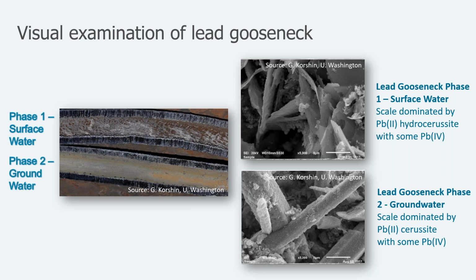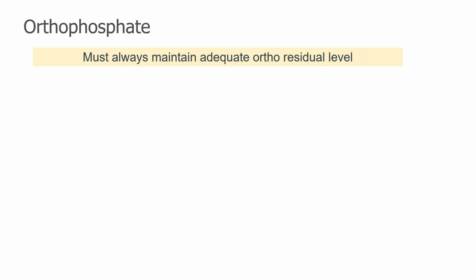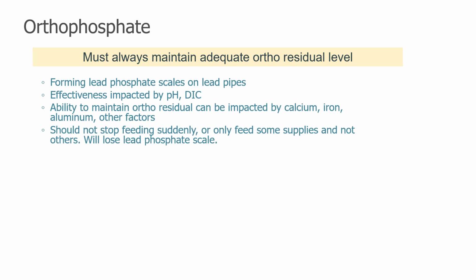So you can't just match pH of a groundwater and surface water and assume that you are going to be forming the same lead species. So the goal here is to avoid alternating these sources or have a controlled blend as often as possible. Some lessons learned with orthophosphate is that once you start feeding orthophosphate, especially for lead control, you must always try to maintain an adequate residual level.